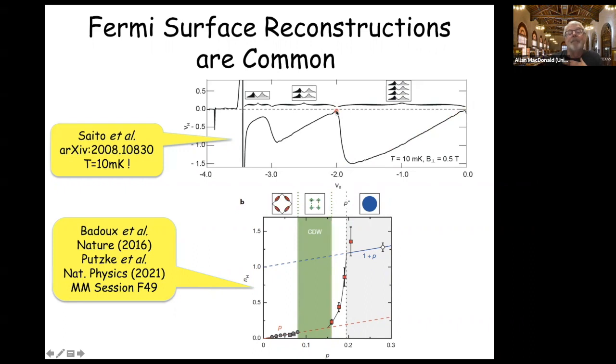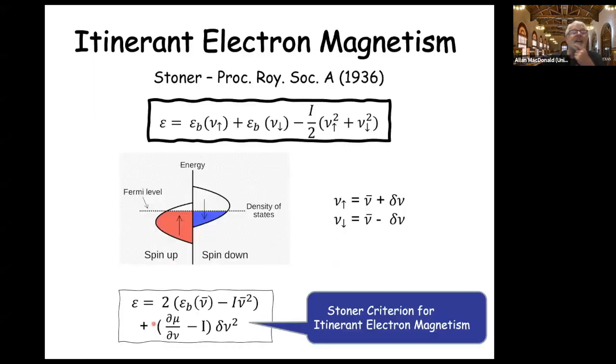And when I go below -2, I start over making a Fermi surface. The interpretation of that is that only 2 of the 4 flavors are partially occupied, and you're seeing the Fermi surface of those flavors as they become less than half full. Interestingly, I won't dwell on this, but very similar things are seen in cuprates, these kinds of jumps in Hall conductivity.